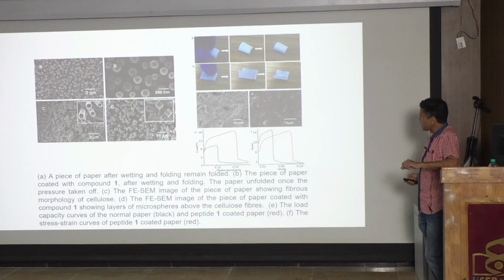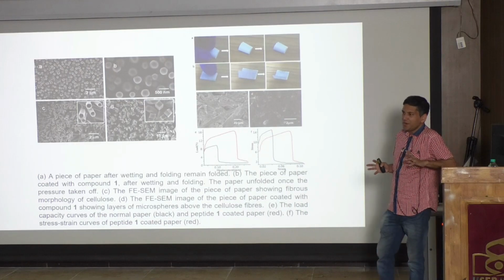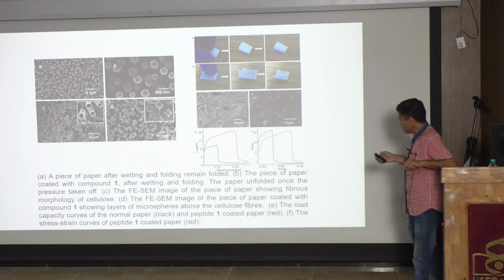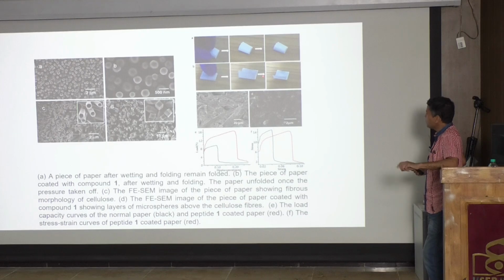And these are obviously hydrophobic in nature, so we took a paper and coated the paper with this hydrophobic moiety. And now you cannot wet the paper. If you put the paper in water, it comes out dry. Without any water, you cannot do that. And we have studied it by AFM and also by load of the paper, so the paper is now much stronger. The paper surface is covered with all these microspheres of this compound, making it very, very hydrophobic in nature.